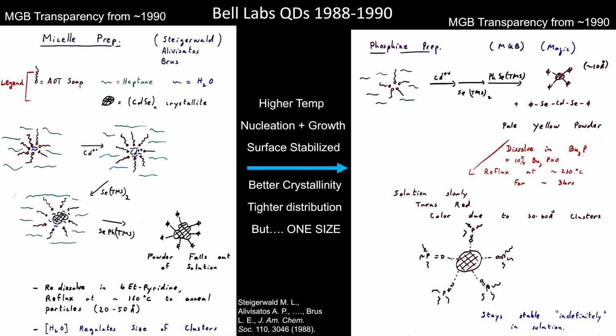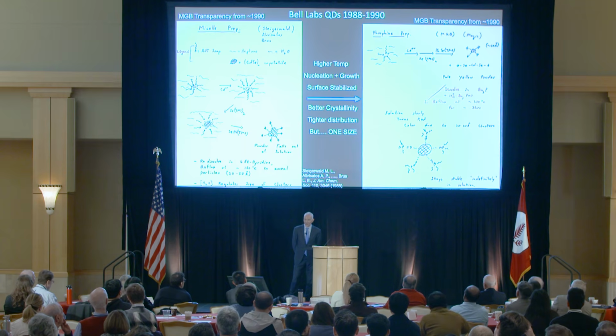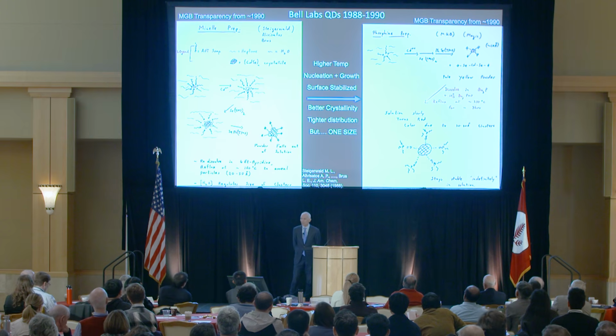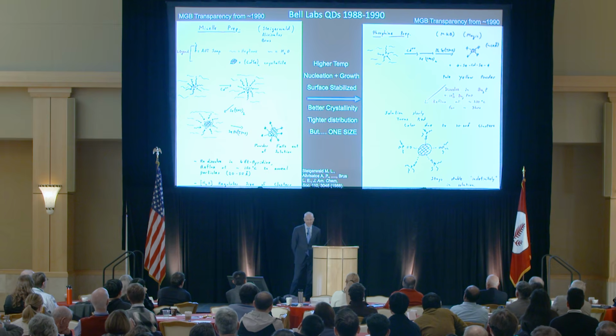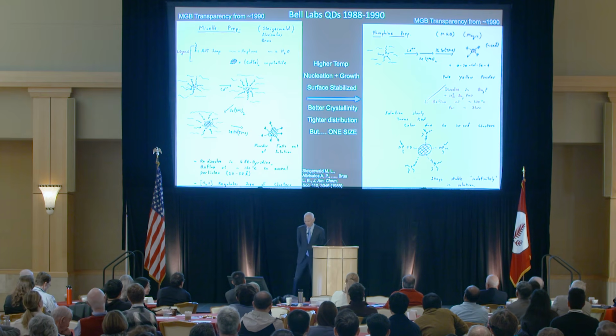When you get a Nobel Prize, you go back through archives and you try to find things. And so you can see that I drew this particle as being completely misshapen, surrounded by phenyl groups, which was also the genius of Mike Steigerwald of realizing that the surface was still chemically active, that you could arrest the surface and then use these phenyl groups to be able to redisperse these things in organic solvents and begin to anneal them. But basically, these were very defective particles, huge size distribution, very misshapen, and the fluorescence that we use today that is applied was non-existent. They were basically emitting white light in very, very low quantity.